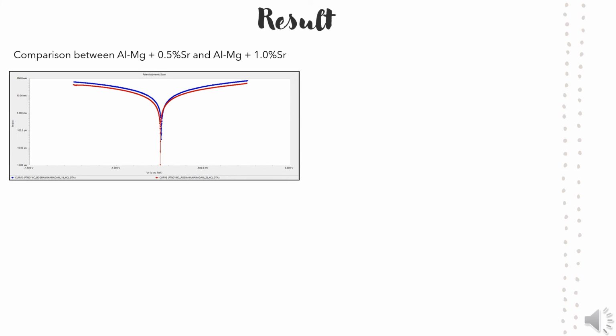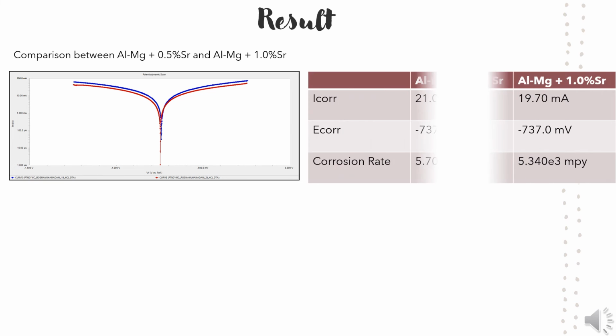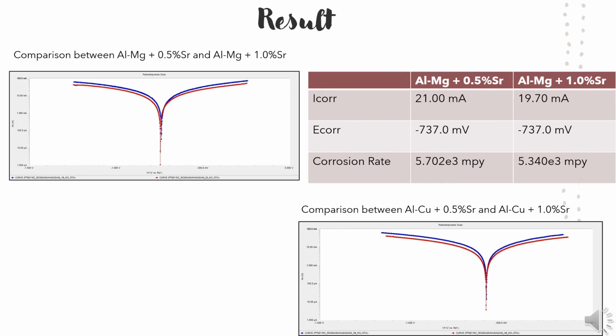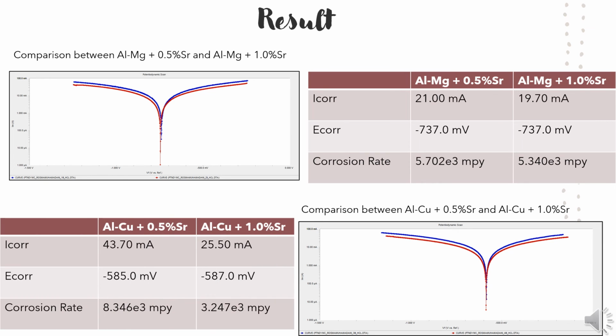This slide shows the result obtained from the experiment. The first figure shows the comparison between aluminium magnesium reinforced 0.5 weight% strontium and aluminium magnesium reinforced 1 weight% strontium. It showed that current density of the sample with 0.5 weight% strontium is higher. In addition, the corrosion rate of the sample with 0.5 weight% strontium also higher compared to sample with 1.0 weight% strontium. The result for aluminium copper samples also exhibit the same as aluminium magnesium when reinforced with strontium.